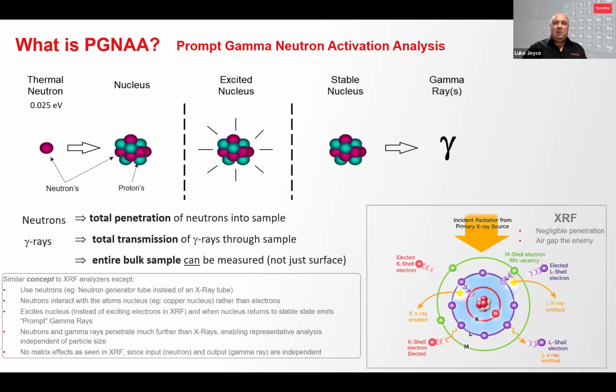One of the key differences with PGNAA is that both neutrons and gamma rays can penetrate entire rocks and sample depths up to hundreds of millimeters, compared to only a few microns of penetration for X-rays. So it can provide representative analysis of large volumes of material independent of particle size.